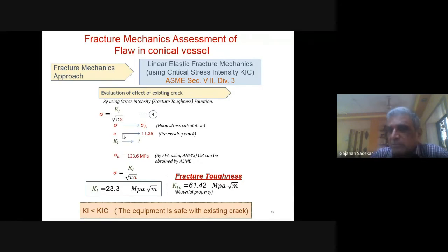But I'm not going to go through these calculations, because Professor Naik is going to tell you about how to calculate the stress intensity and all the related fracture toughness. You will have some lectures in a subsequent session. So I don't want to explain the methodology, but I will tell you what happened as a result. The result was we found that the stress intensity was much less than the fracture toughness. If you see, the KI value is 23.3 and KIC is 61.42, it was less than that. So we said the equipment is safe with the existing crack.